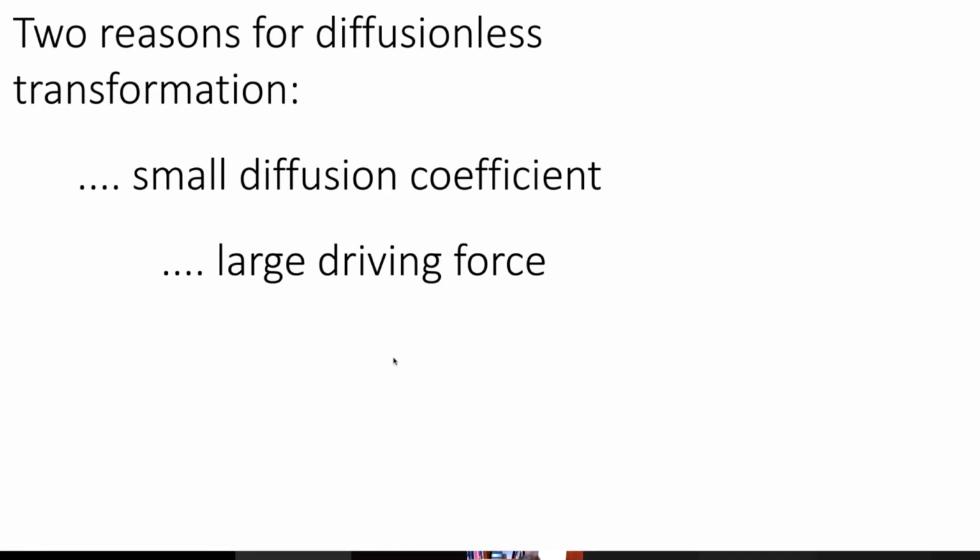So we expect martensitic transformation in pure iron to happen at a higher temperature than martensitic transformation in an iron-manganese alloy, because the driving force for transformation in pure iron is much greater than in an iron-manganese alloy.